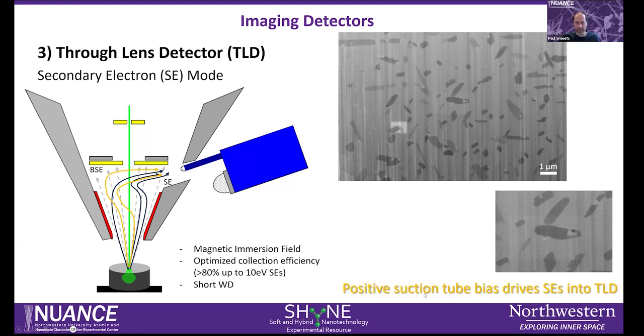And again, if we apply that positive bias on our detector, we can drive the SEs into the high resolution detector. This is an example here on the right of a cross section of an alloy, where you can see first of all a lot of these type of curtains, so we get more predominant surface information from our secondary electron signal here.